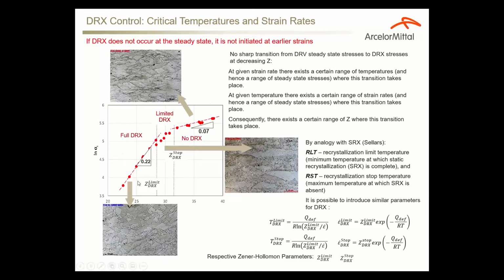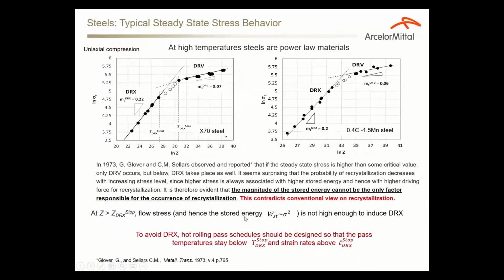Dynamic recrystallization control can be done if we consider that steels are power law materials. When we plot steady state stress against the Zener-Hollomon parameter, we found different microstructure depending on Z, and we introduced two, or basically four, limiting parameters, either temperature or strain rate, that represent the boundary between full and partial dynamic recrystallization, and the boundary between partial and zero dynamic recrystallization. Or we can introduce the respective Z parameters. So the convenience is that we know the strain rate or rolling speed and temperature, and we could use either of them to set up the no recrystallization or full recrystallization rolling schedule.